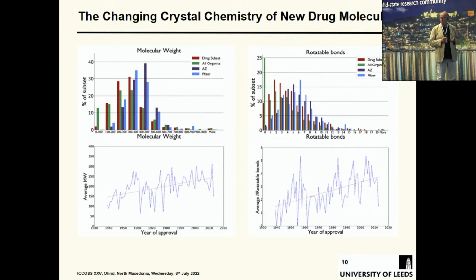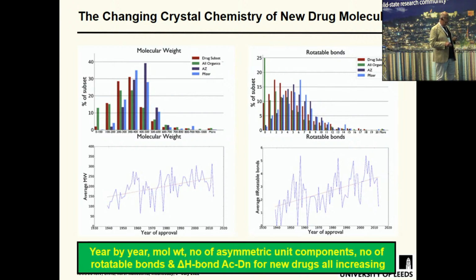So if you're in a small molecule, you can accept that maybe hydrogen bonds and electrostatics play a big role. But once you get to big molecules, you know that dispersive van der Waals interactions are really a big determinant factor. Year by year, the molecular weight, the number of asymmetric unit components, the number of rotatable bonds, and the delta H-bond acceptors minus donors is all increasing. It tells you the direction in healthcare and the molecules we need to be capable of modeling.